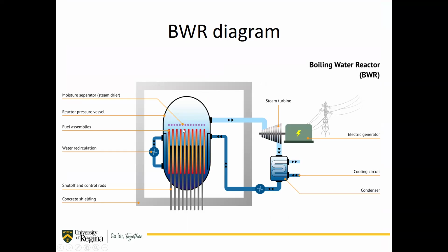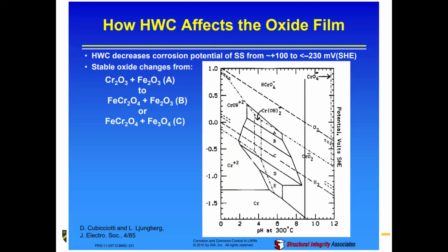Whatever happens in that reactor pressure vessel can absolutely make its way to the turbine hall, which is where you need to do maintenance. And so you have to be very acutely aware of what dosage you're exposing your workers to. The control over that is much trickier. This ostensibly small change in the corrosion products that are forming, this crud as people often call it, changes the form of the crud forming in the reactor itself, from chromate and hematite to these other phases, hematite or magnetite or whatever.